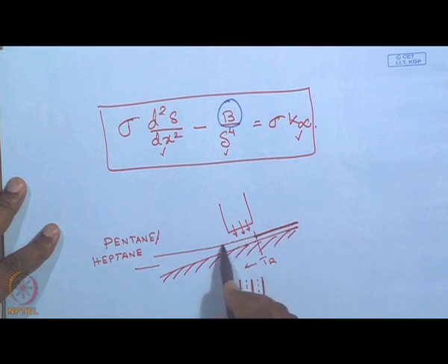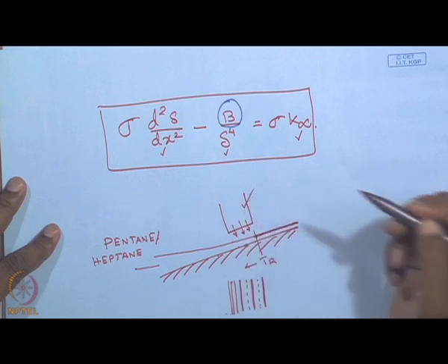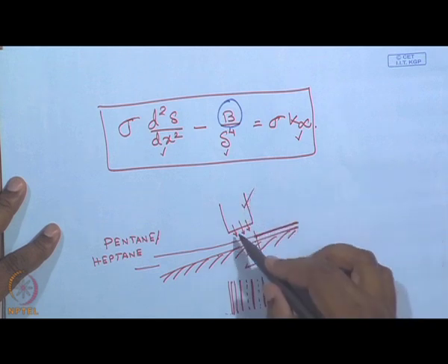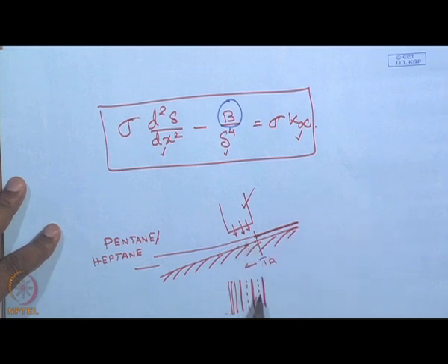As the film becomes thicker, as I move towards the thicker portion of the film, the fringes will become close to each other, and after some point it will not be possible to distinguish between two adjacent maxima or minima. How far, to what distance, we can go depends on the magnification of the lens that we are using and the light level of operation. So, we get alternate dark and bright fringes.